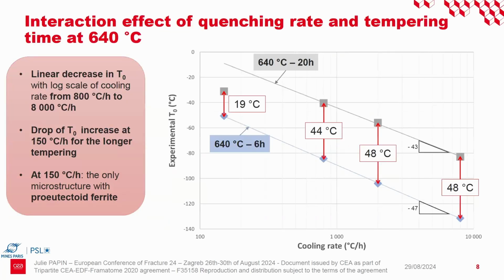Now we represent the reference temperature obtained during our experiments as a function of the cooling rate in log scale. And we can note that for the two tempering conditions, we have a linear decrease in T0 with the log scale of cooling rate from 800 to 8,000 degrees per hour. But this point is particular. We observe a drop of T0 at the quenching rate of 150 degrees per hour for the longer tempering time.